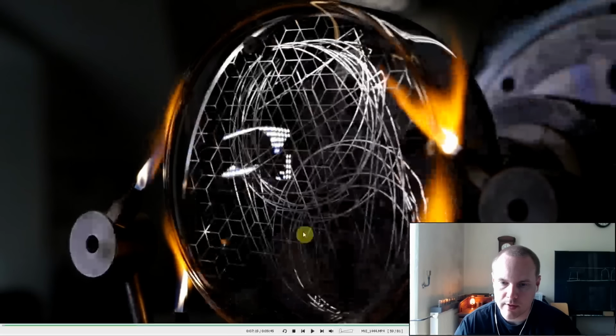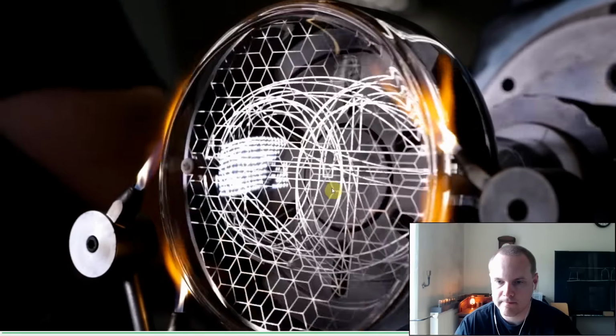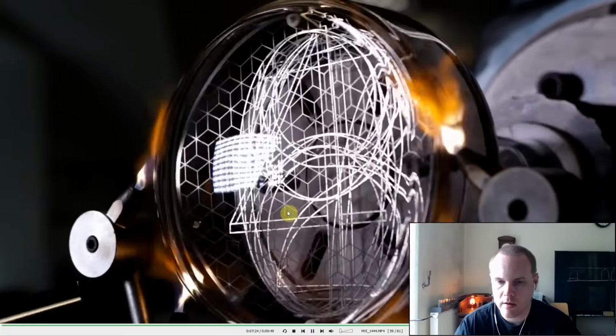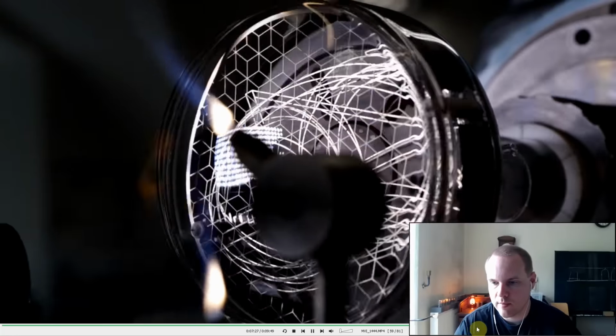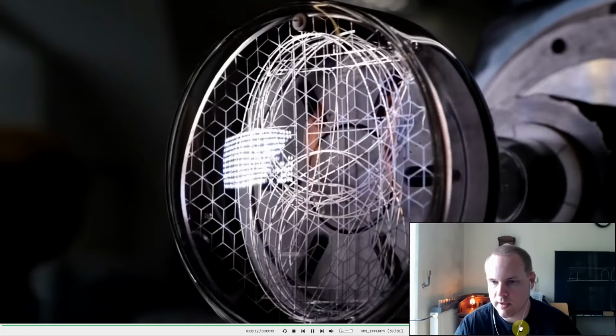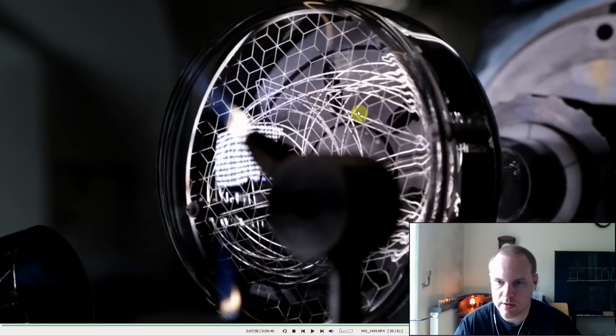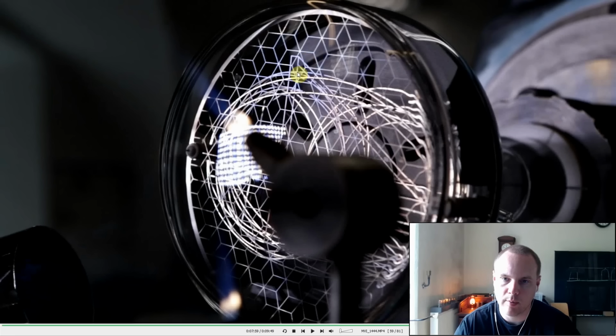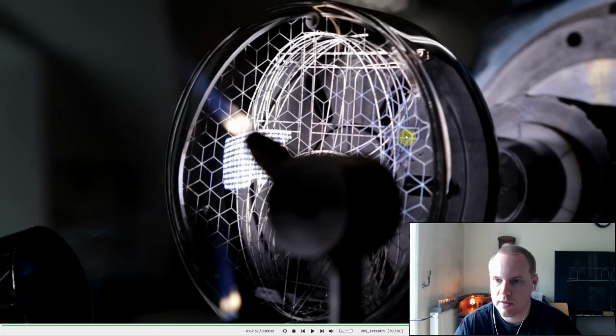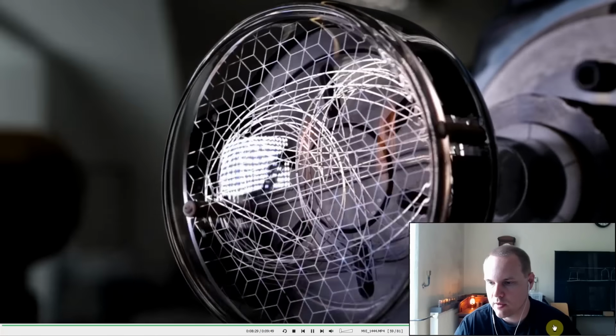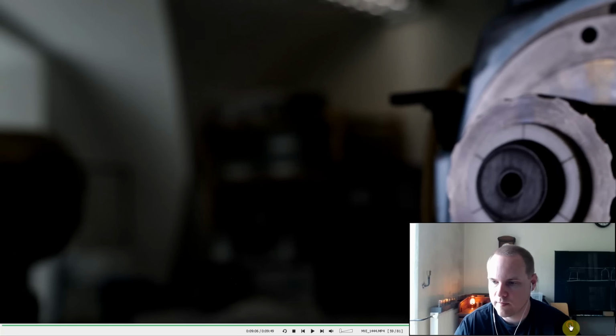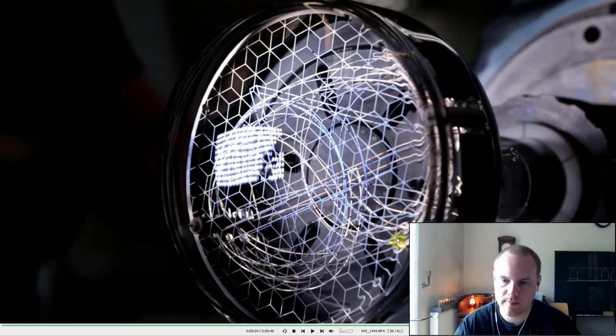And now we start the annealing process. I will skip a little bit, and you can see already here the digits are turning blue, especially at this part of number 4, which is close to the glass but not shielded by the wing of the anode cap. Here we can see it's completely blue. So in this case we saw clearly that the oxidation took place during the annealing process.